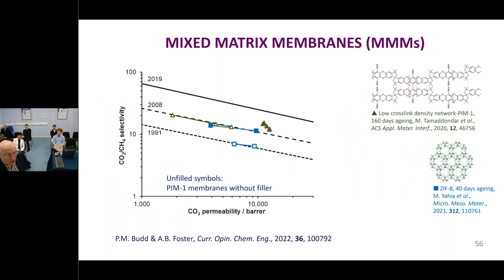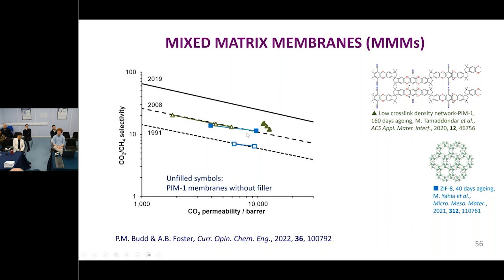Another thing we do is make mixtures to form what's known as mixed matrix membranes. There, it's all about getting compatibility between the different phases. And one way we've done that is by making a filler, which is effectively a variant of our own polymer. And also, we put bits of our polymer in to improve the compatibility. And we can see that we can go from a situation where we have a big loss of permeability to a situation where we have a very tiny loss of permeability over 160 days, coupled with an increase in selectivity. So you can actually have quite a big effect on the results.